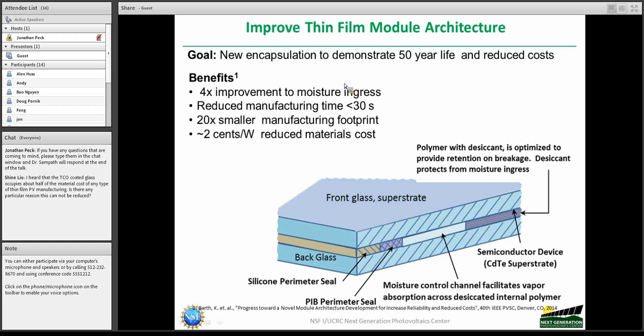But the design that we have come up with, and this has actually been done on a commercial scale in a modified way at Abound, and since then a lot of refinement has happened to improve the module architecture. What it involves is two glass plates with a perimeter seal involving silicone. Now, the current designs do not use a silicone layer. They use organic polymer here, and organic polymers degrade under UV, and there is a potential possibility with the current structure which the silicone layer avoids.